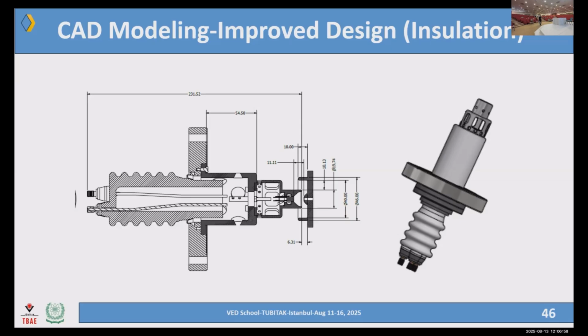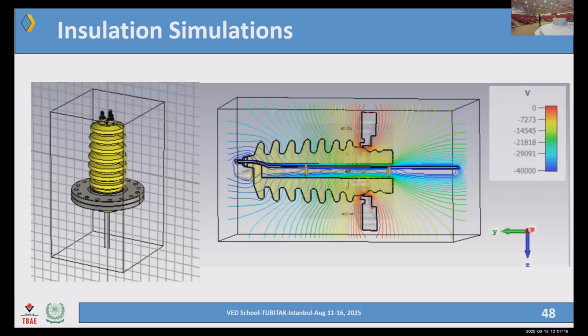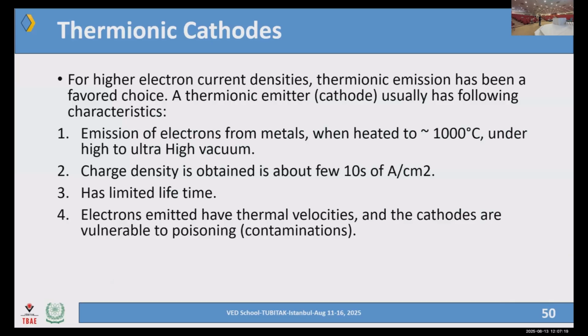Tungsten can emit high rates of electrons, but that is at even higher temperatures. It's around 2000, 2200 Celsius, 2400 degrees Celsius. But that temperature range is going to kill it even more. But for low temperatures, they're not too low, the 1000 degrees Celsius, even then, it is very, very hard to maintain the temperature stability. To remain in this region, the ultra high vacuum region, is literally a challenge. It's not impossible. We and many others do it, but of course, this is the condition that you can do,